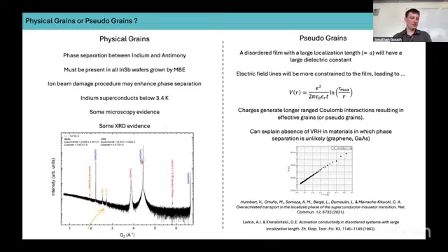So we can see peaks for the gallium arsenide substrate, the indium antimonide thin film, but we also get these very weak peaks corresponding to indium. So that's one explanation. Another explanation is slightly more complex and relates to pseudo-grains, which occur in systems with a